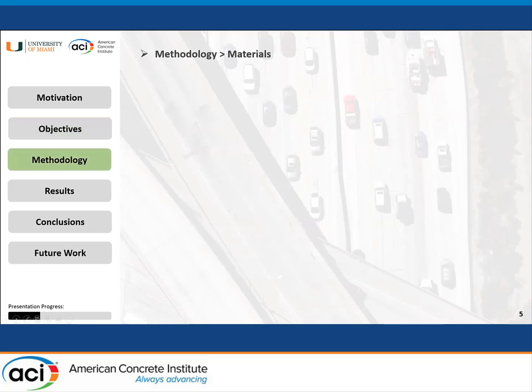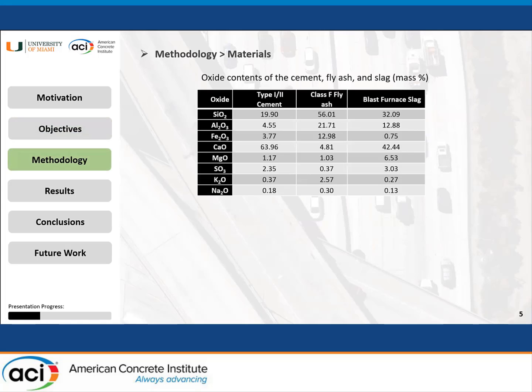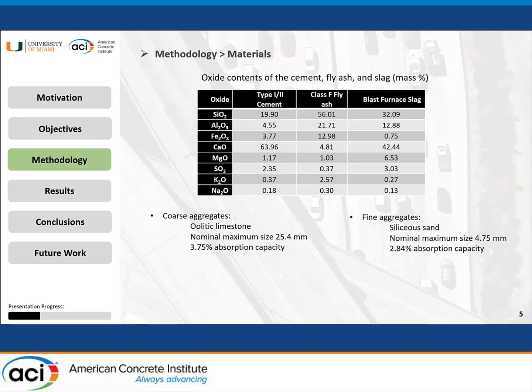So let's talk about our methodology and the materials that we used. In this table, you see that we use type 1-2 Portland cement, class F fly ash, and blast furnace slag. The coarse aggregate was oolitic limestone with a nominal maximum size of 25.4 millimeters, and the absorption capacity was measured to be 3.75%. And the fine aggregate was silica sand with a nominal maximum size of 4.75 millimeters with absorption capacity of 2.84%. As our de-icing salt, we use commercial de-icing calcium chloride with purity more than 95%.